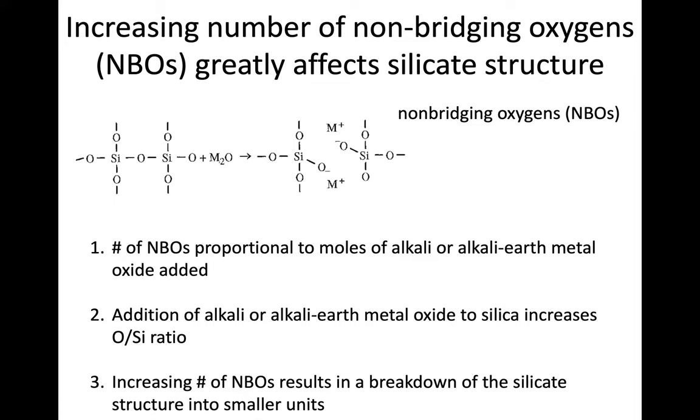The other effect is that increasing the non-bridging oxygens breaks down the structure. You can see that by adding these M⁺ metal oxides, we've broken up this network. This was bonded together, but by adding metal oxide we've broken apart this network into smaller and smaller units.